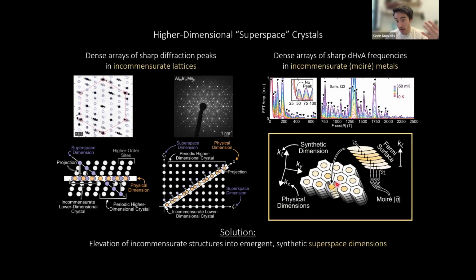We'll project from higher dimensional Fermi surfaces, and particularly a 3 plus 1-dimensional Fermi surface, down into our physical space. And this is generated instead of by lattice mismatches, but by momentum mismatches due to the Moiré superlattice. So we kind of had a feeling that this might be true, that there might be some connection, but it was really gratifying to see that a lot of this popped out of just standard Lifshitz-Kosevich theory for understanding Moiré metals. So in collaboration with Nisarga Paul and Filippo Gaggioli and Liang Fu at MIT, we were able to